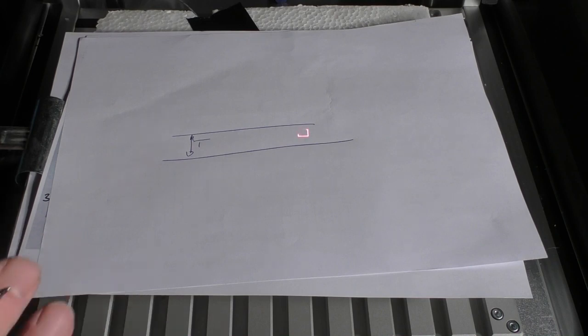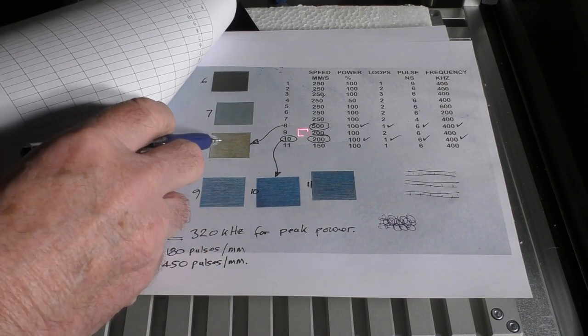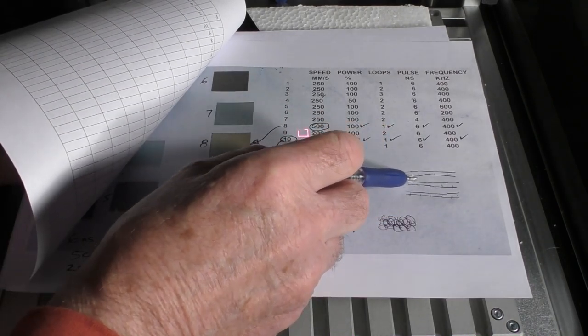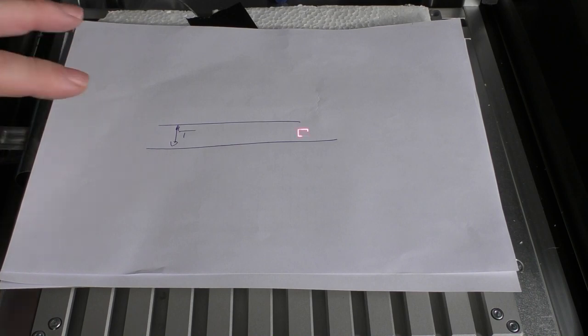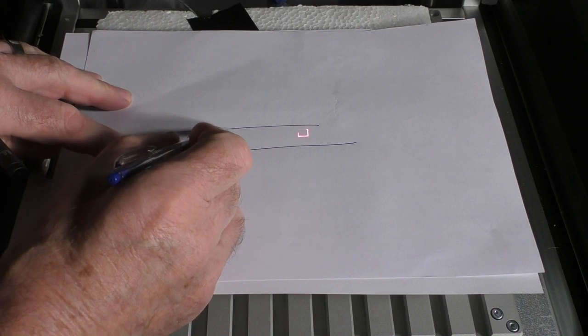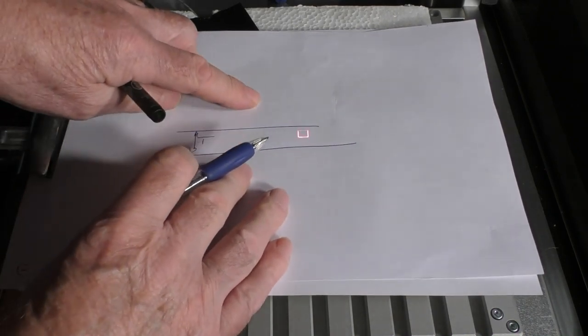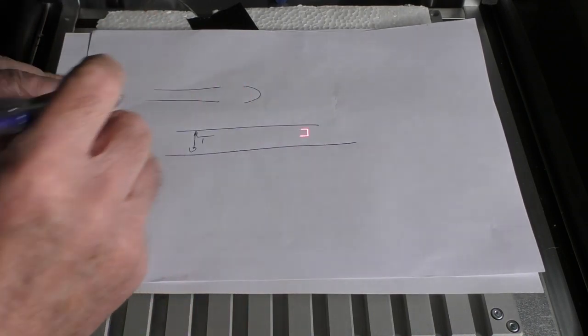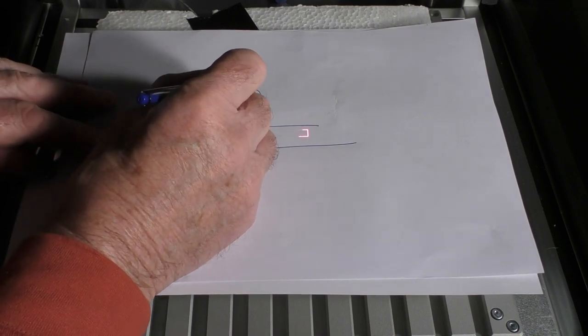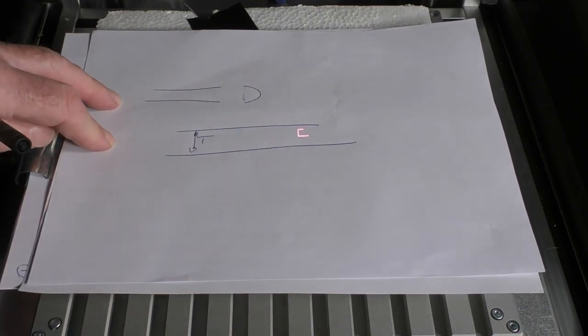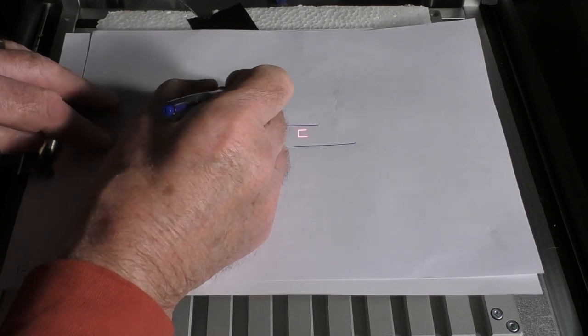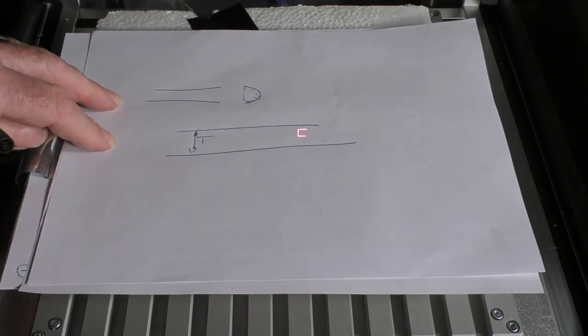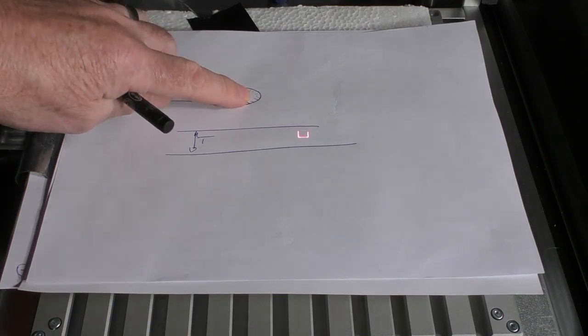Now there's no doubt that the thickness of the oxide film is the cause of the colors, but what these tests show is that because we've got lines with colors in them, we must be forming this oxide layer in a different way than what I'd originally anticipated. Whereas I thought that we might have to fiddle around with this surface here and build the layers up and down, I think that what we're doing is we're cutting into the surface and melting the surface. So we could either be melting the surface and when the surface resolidifies we're getting this oxide film on the surface, or we're vaporizing this area and we're leaving an oxide film on the surface within the groove. That's what it looks like from the pictures under the microscope, this second situation.